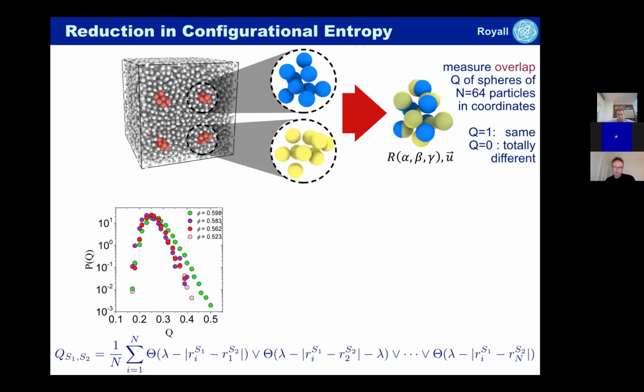Another thing we've been able to do with this particle data is to make some kind of measure of the configurational entropy. I said that in the thermodynamic picture of the glass transition, the configurational entropy would decrease, and we can obtain a measure of that by looking at something called the overlap. The overlap is Q. It's defined at the bottom of the slide. The important thing is that if I take particles from one place and overlap them with another place, here I take my blue particles from one place in the system and put them on top of yellow particles from another place in the system. If they are in the same position, the overlap is 1. And if they are not at all in the same position, the overlap is 0.